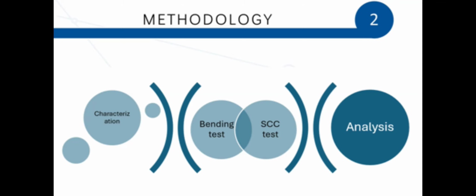Each steel was evaluated with different load percentages relative to the yield strength of each material. The test environment was an NS4 solution with a near neutral pH in an autoclave at 80 degrees Celsius, plus or minus 5 degrees Celsius. The solution was purged with a gas mixture of 5% carbon dioxide and 95% nitrogen. After the 6-month testing period, the samples were removed from the autoclave and a pit count was performed for evaluation. Subsequently, these pits were examined using scanning electron microscopy.